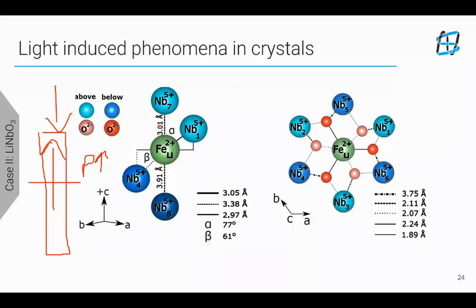So along the polar axis, an electron has more tendency to go towards the niobium 4, especially when the light excitation is parallel to the polar axis. And when we look at the cross-section in the AB plane, it can go anywhere, basically, but then the angles and the length of the oxygen above and below really determine exactly where the electron would go, either to niobium 1, 2, and 3 above, or niobium 5, 6, and 4, which are below. So this actually depends upon the light polarization direction, which kind of gives a push to the electron. That is what we think. And once we see the symmetry, we know that there's asymmetry and there's more tendency for an electron to go to the nearest niobium site.